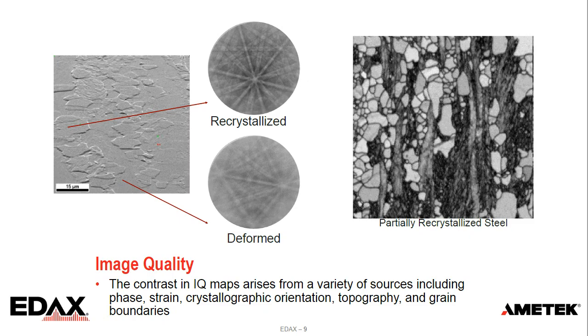As we come closer to grain boundaries, the patterns can start to overlap and the overall intensity decreases. So this slide just shows an example of a recrystallized pattern and a deformed pattern. You can see the sharpness difference. You can kind of see the intensity difference, but if we map that out on a grayscale map, you can clearly see the recrystallized grains are bright and equiaxed. The deformed grains are much darker and more elongated in the microstructure.